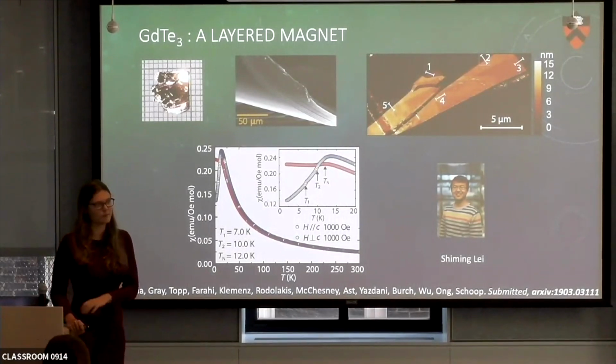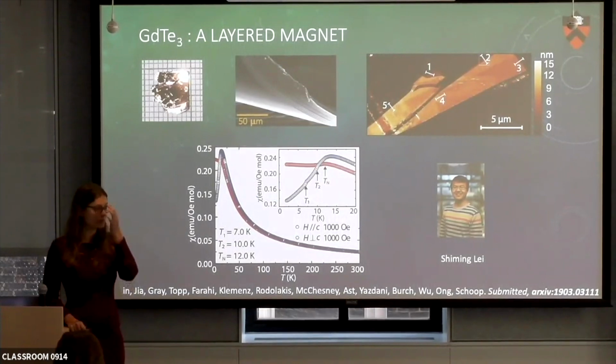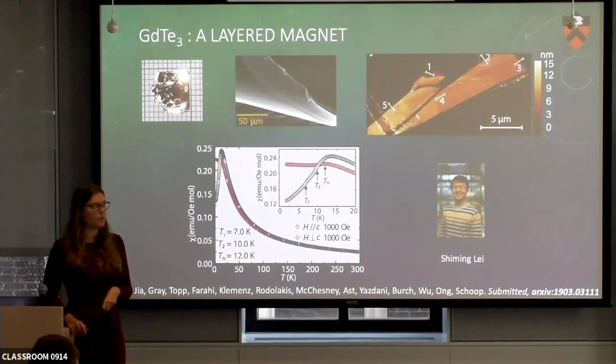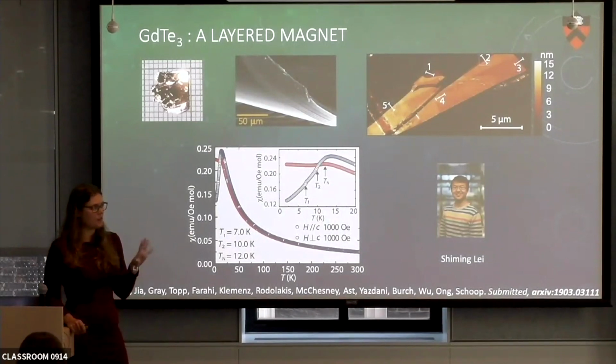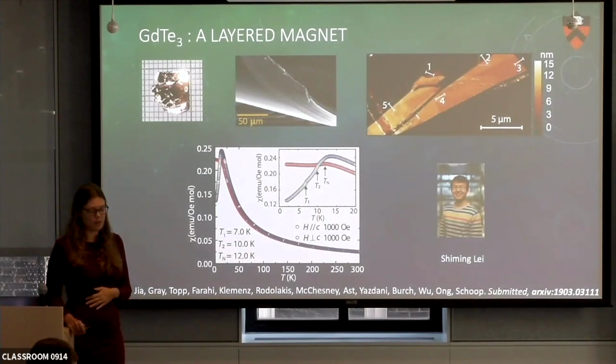So then for the spin, are they collinear or? You don't know. So I couldn't do neutron diffraction on this because it has gadolinium, which eats all neutrons. We did the cerium analog and shipped it for neutron, but then the Oak Ridge time got cancelled last year, and now we're waiting for the next beam cycle. But also they are very different depending on the different rare earths. So I'm not sure if what we learned from the cerium will happen for the gadolinium. I'm trying to find collaborators who do X-ray studies with us for the magnetic structure. These are very complex magnetic structures.